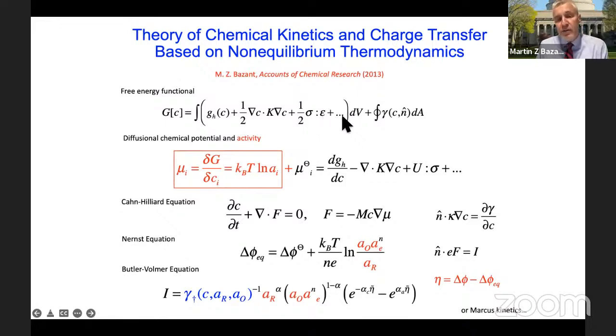And of course, you can add other terms as well, such as having to do with electric charge, electrostatic energy, and dielectric polarization energy, or other effects. There also, importantly, can be surface effects in these particles where, for example, the interfacial tension of a surface is a function of concentration, and also the normal vector prescribing the orientation of that surface.